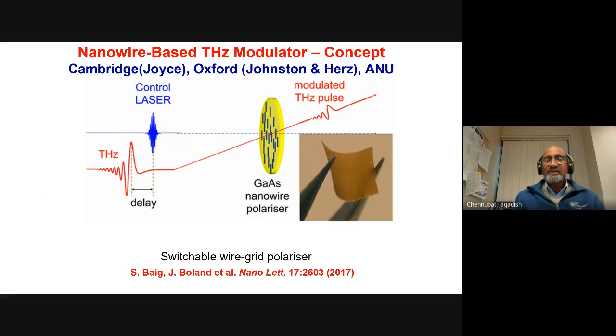So now if I come with the laser pulse, and the polarization of the laser is aligned to the nanowire, it gets absorbed and then generates photocarriers. Next you come with the terahertz pulse, it interacts with the carriers and gets modulated, for example reduced in amplitude. If the polarization is perpendicular, it doesn't get absorbed that efficiently, and in the process the modulation is not that high. This is joint work with Sarwat Baig and Jessica Boland, who is now a lecturer at the University of Manchester. Sarwat is working in a company.